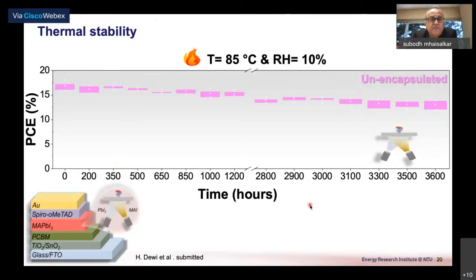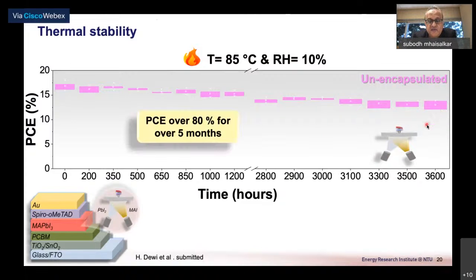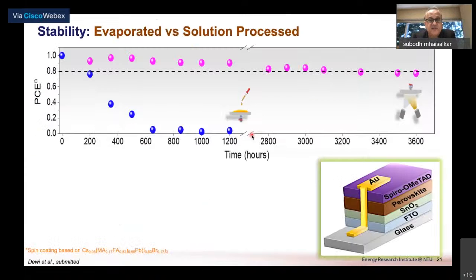In addition to room temperature studies, we also expose these perovskites to higher temperatures, and in this case, 85 degrees centigrade, and these samples were also unencapsulated. These were stored in this condition for more than 3,600 hours throughout the lockdowns that we had this year because of COVID. And as you can see, there is a certain level of degradation, but the degradation is not as significant as has been seen with solution process devices, as I'll also share with you on the next slide. So the PCE of more than 80% could be retained for more than 5 months.